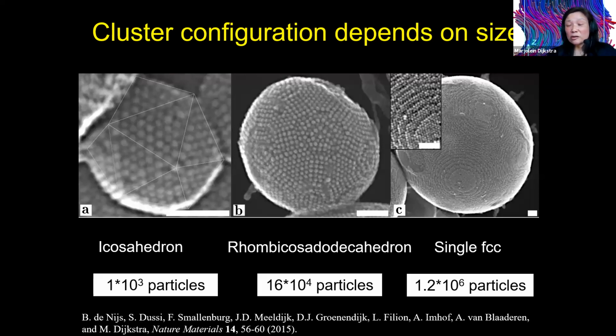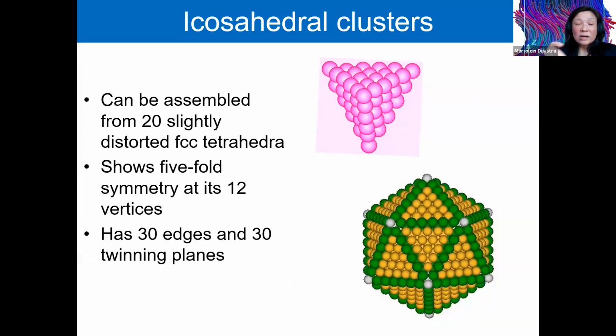So these icosahedral clusters are very intriguing. They consist of 20 slightly distorted FCC tetrahedral domains. These pie slices are all pointing inwards. They all meet in the center of this icosahedral cluster. At the outside, you will find five-fold symmetry at the 12 vertices. And so there are 30 edges and 30 twinning planes inside this icosahedral cluster.